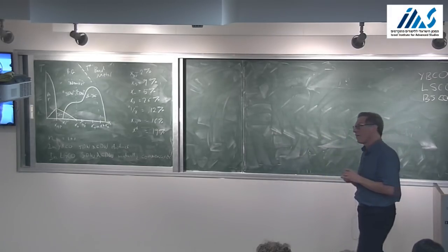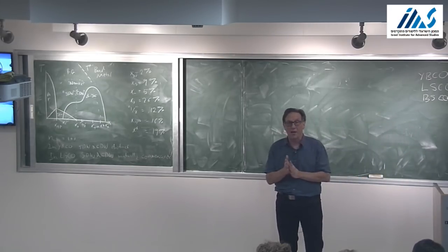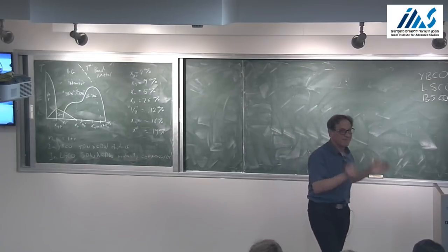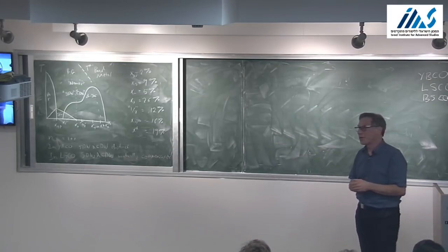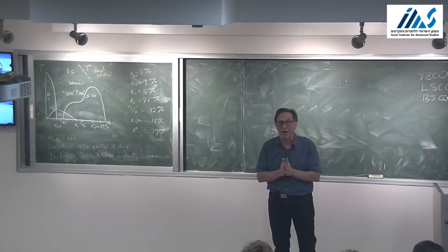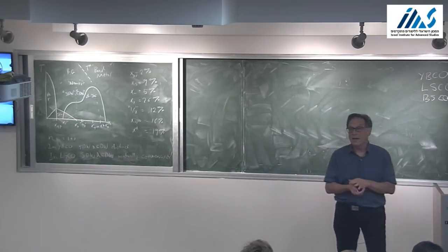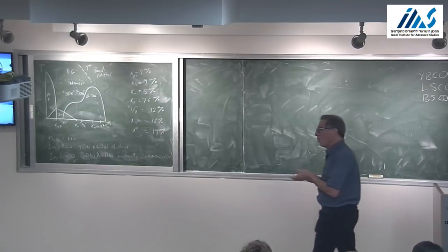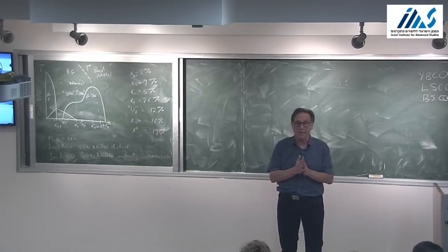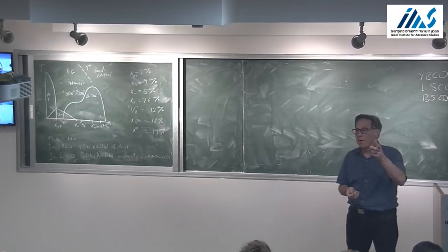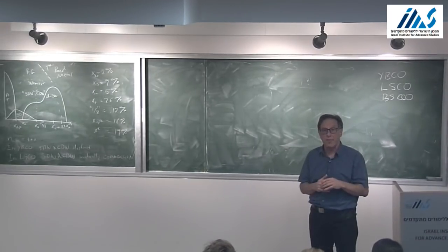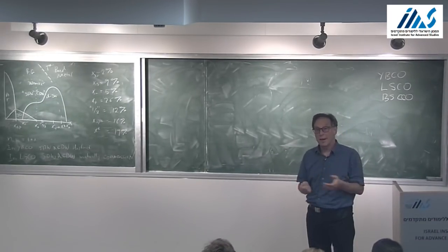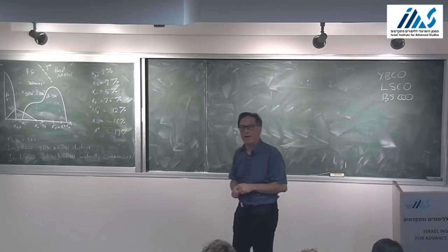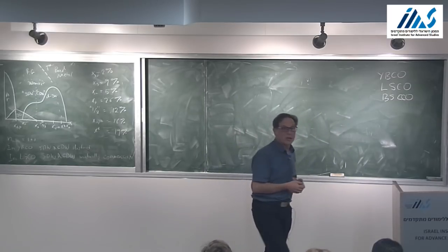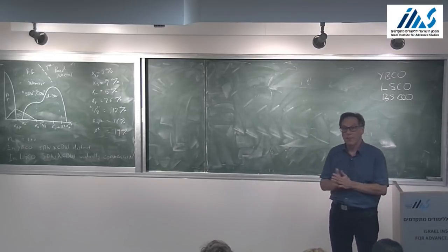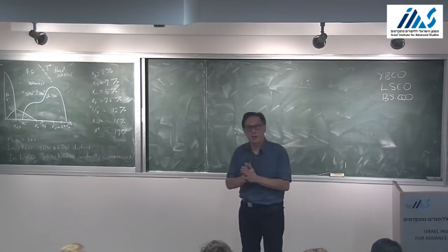And in particular, for this structure, there is a Jahn-Teller distortion, which has to do with some subtle distortion of the copper oxide octahedra. And he had the idea that that Jahn-Teller coupling would produce particularly strong electron-phonon coupling, and that moreover, because it involved oxygen phonons, oxygen's relatively light, so the phonon frequency is very large. So the combination of a strong coupling and a large frequency, he thought, would lead to high temperature superconductivity.